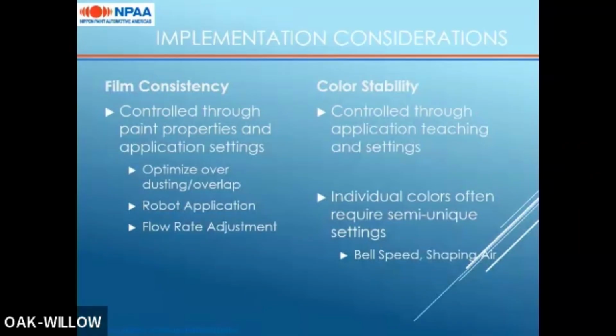We're also able to ensure, or you need to make sure, that you have good flow rates adjusted for the film build targets, with most of the colors that we currently make using a flow rate of between 90 and 140 cc's per minute. Then for color stability, this is again controlled through application teaching and settings. Many individual colors require semi-unique settings, particularly for bell speed and shaping air.